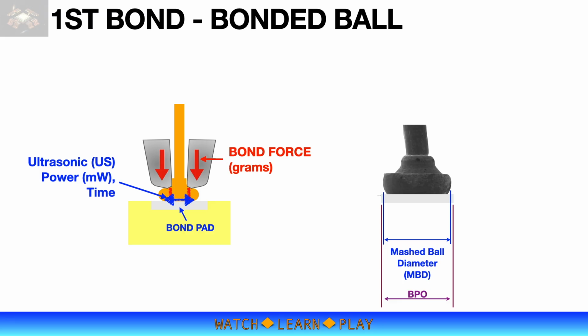On the low side of the limit, while 2 times wire diameter will very likely be inside the bond pad, it is likely to result in a lower bond strength because the contact area will be smaller. Because of the inherent shape of the bonded ball, the contact area is always smaller than the mash ball diameter. Also, the bonded ball height should be around 0.6 to 0.8 times the wire diameter.